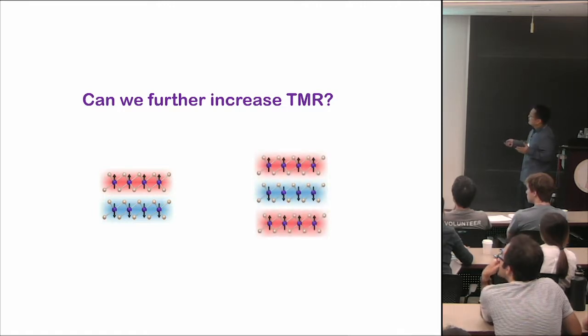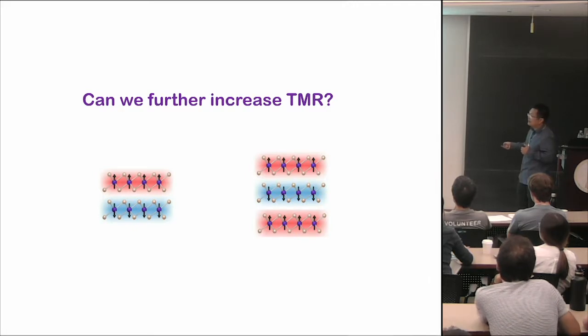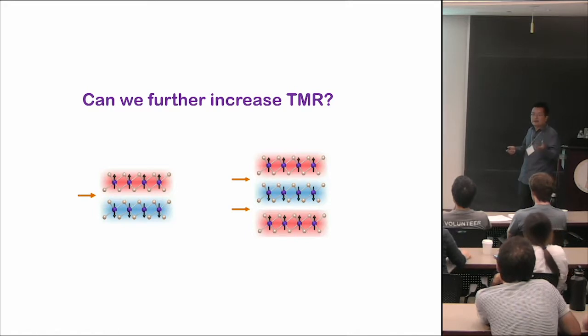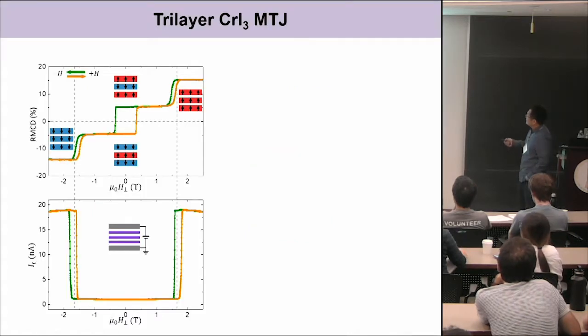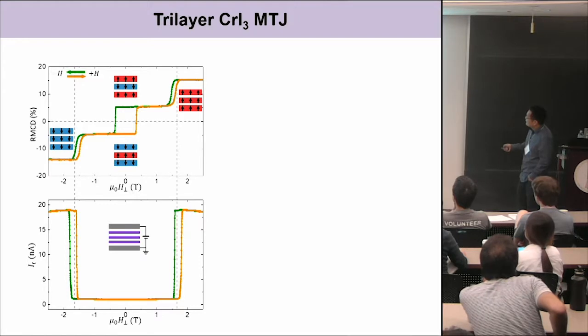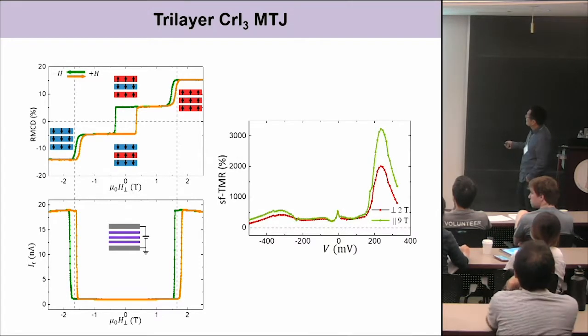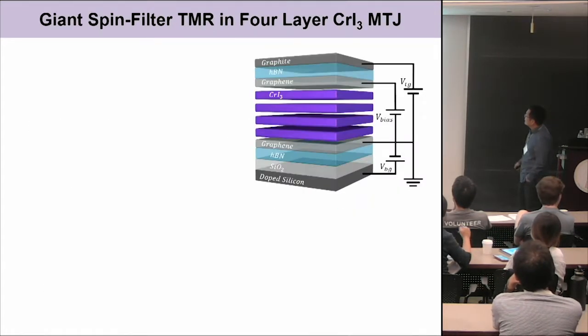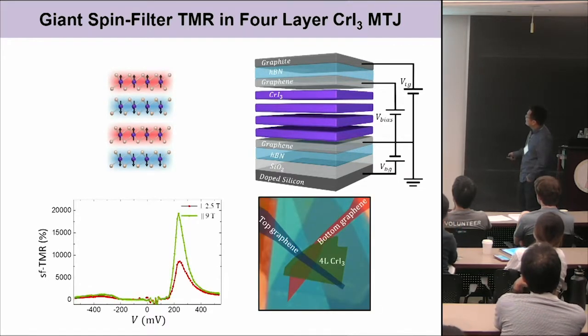If you go to a trilayer, you have two interfaces compared to the one interface in the bilayers. Therefore, you can already imagine the tunneling magnetoresistance will increase. This is exactly what we see for the trilayer. We have this Kerr rotation map, and with the tunneling current measurements, we observe the TMR increase to about 3,000%. And we can keep doing that. Go to 4 layers, for example, then the interfaces with antiferromagnetic coupling increase, and the TMR can go as large as 20,000%.